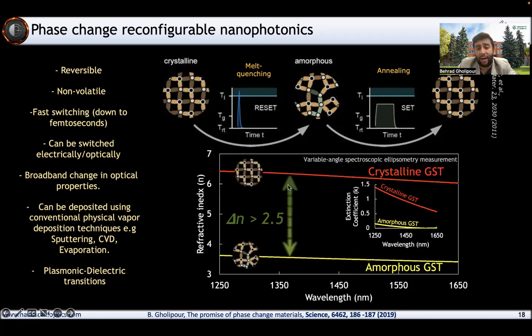So just to give you an outlook, across the telecom band, you have as large as a 2.5 change in refractive index. If you're familiar with much of the switchable materials that we use in optoelectronic industries and computing industries, the refractive index that we generally look at in these systems in lithium niobate, for example, or in the silicon derivatives that rely on thermal optic properties, or even ITO with the carrier modulation and the transparent conductive oxides, there are refractive index changes on the order of, maximum 0.4, 0.5, really much lower than that in most cases. This is a much larger change in refractive index, more than 2.5 in N.